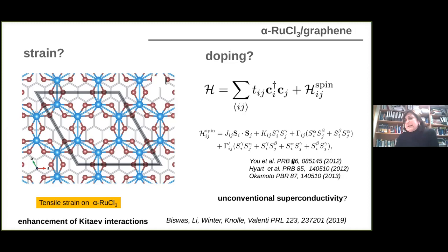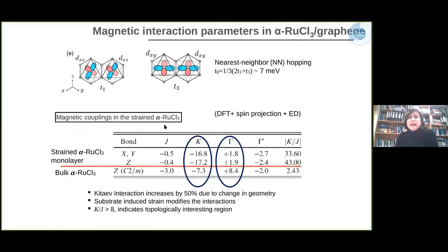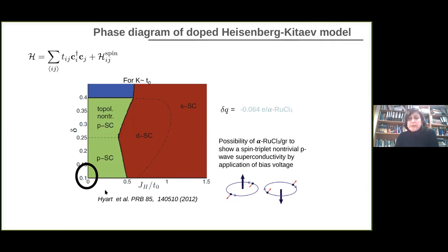So if we now take into account this new Kitaev model with some doping, there have been various works in the past trying to understand the possible phases of this type of models. And here I'm showing, for instance, the phase diagram obtained by Hyart and collaborators, where they considered a slave boson formalism to investigate a doped Heisenberg-Kitaev model. And this is the charge I was trying to find the number for. By considering this charge transfer, in the case of ruthenium trichloride, the electrons that we bring there from the graphene, we would bring the system into this region of possible P-wave superconductivity. And in fact, tomorrow, Johannes will talk a little bit more about this possibility of P-wave superconductivity in the system that could maybe be induced by applying a bias voltage, by trying to bring the system more in this direction.